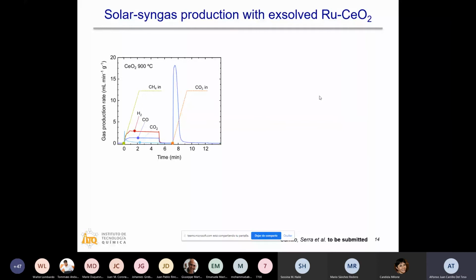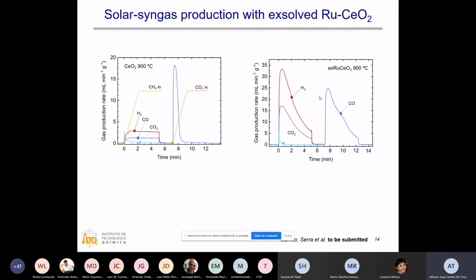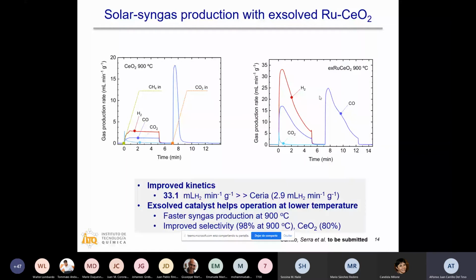We also tested our material with exsolved ruthenium nanoparticles, and we observe a very interesting and remarkable increase in the production of both syngas and carbon monoxide during the CO2 splitting reaction. We observe an order of magnitude increase in the hydrogen production rates with the exsolved ruthenium material, 33 milliliters of hydrogen per minute per gram, whereas for ceria it's about 3. We also observed that we can improve the selectivity towards syngas, 98% for this material, whereas for ceria it's just 80%. We also evaluated different temperatures.